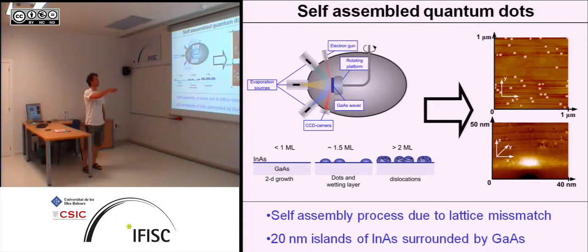This is an AFM picture from basically this plane. You see all these single dots here are single quantum dots, and they're pretty regular in size and shape. The next image is a cross-section through a single quantum dot, and you see the material corresponding to the bright part is indium arsenide, while it's completely surrounded by gallium arsenide. That means first you have a self-assembly process, so you don't actually have to worry about anything but the thickness control of these layers.